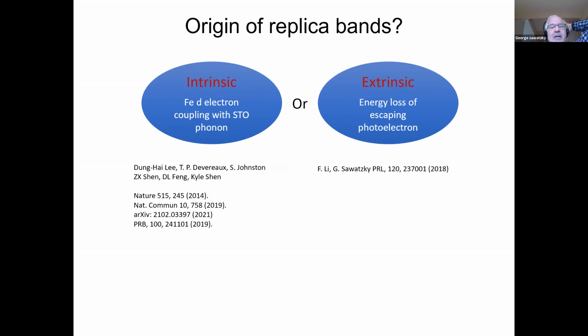Now, I just want to talk about these replica bands, but I want to be very short because I want to get to the rest, which is more interesting. There's two ways of getting these replica bands. One way is that there is an electron phonon coupling of the d electrons, which are the electrons basically at the Fermi energy of iron, coupling with the phonons of strontium titanate. And it would have to couple with these Fuchs-Kliewer type phonons, and I'll describe them in a second. Those are at about 100 millielectron volts. They're the longitudinal optical phonons in the bulk; the transverse optical phonon corresponding to that longitudinal optical phonon is your soft mode. It's at 10 or 15 millielectron volts.